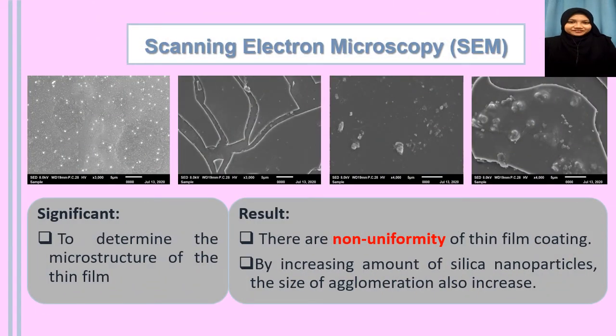Okay, the thin film coating is also characterized by using scanning electron microscopy (SEM). The significance is to determine the microstructure of the thin film. For the first picture, it shows that there is a white precipitate on the untreated glass slide. This happened due to the impurities present on the glass slide. For the second micrograph, it shows that there is a crack on the coating. It happened due to sample damage during the cutting process.